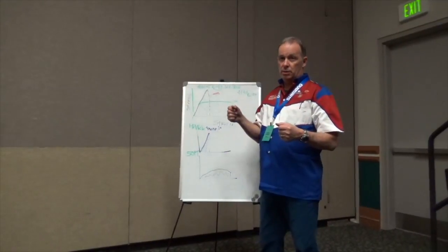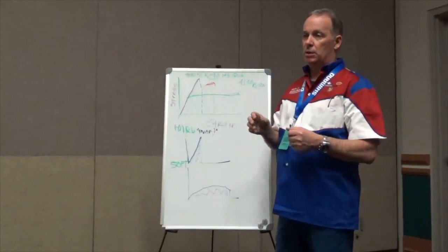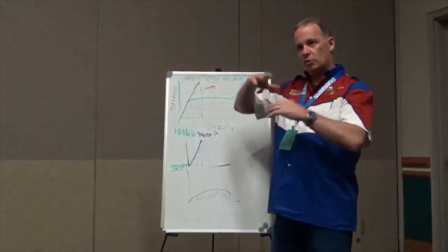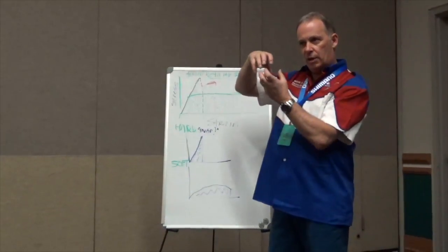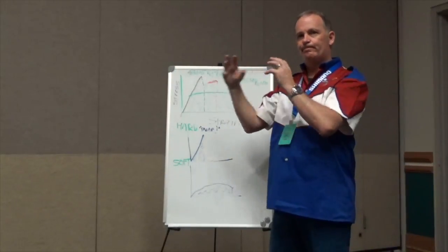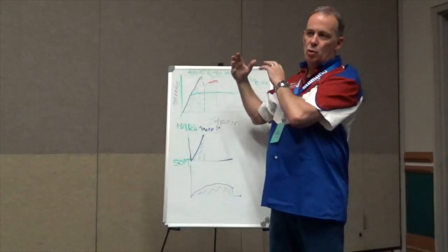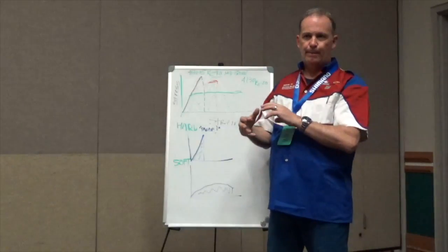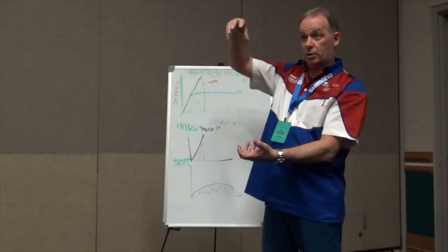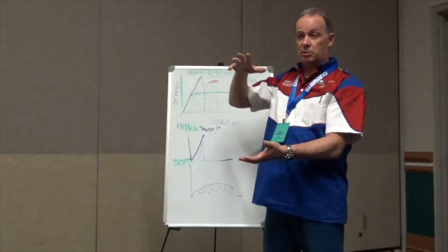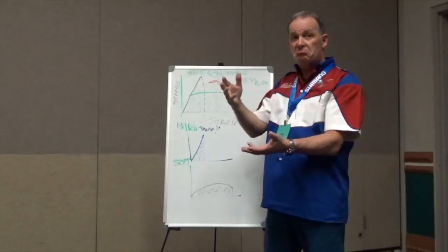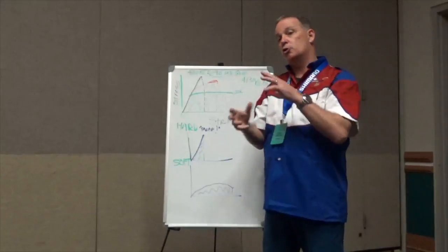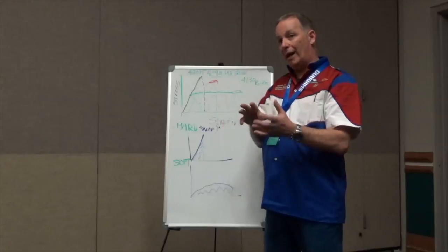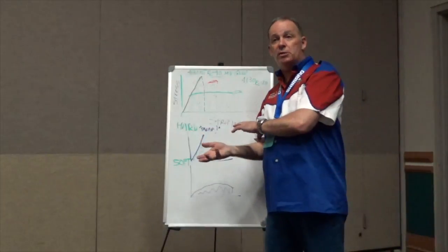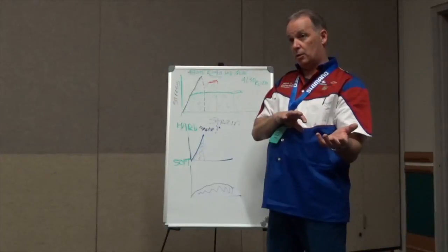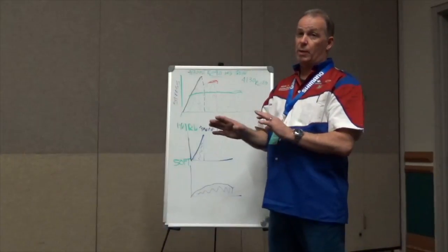When you heat treat, it does a similar thing, but it's not exactly the same. What happens is when you heat the material up, those bonds, those crystalline bonds that are holding this stuff together, start to excite, they start to vibrate. And then, if you cool that material really quickly, then some of those bonds are in a stretch state like the spring that's been pulled out. Some of them are in the spring state where it's been compressed. Some of them are in neutral state. So you're storing energy in those bonds. You're just doing it a different way. And sometimes the heat treating way is better. Sometimes the cold working way is better. Sometimes a combination of both is the best.